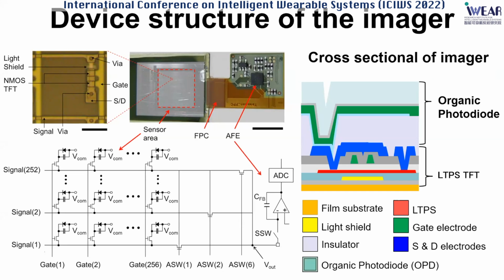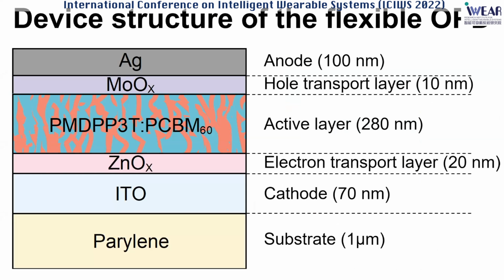So we manufacture the low temperature polysilicon TFT that was originally developed for the display. And then we put the intermediate insulating layer and then complete the fabrication of organic photo detectors with keeping the whole process temperature low. And this is the device structure of flexible organic photo detectors. We utilize the 70 nanometer thick ITO as a cathode and deposit the zinc oxide as electron transporting layer. And the active layer is a mixture of PMDPP3T and PCBM. And finally, we put the molybdenum oxide and silver anode.